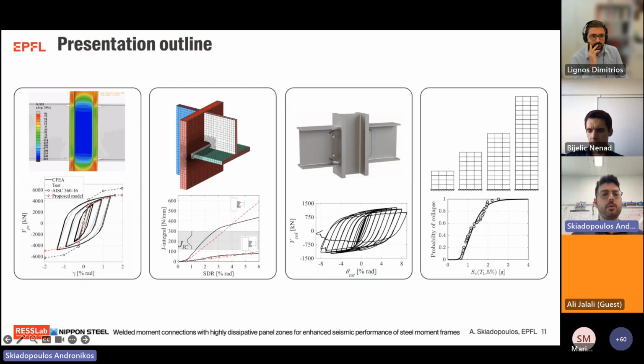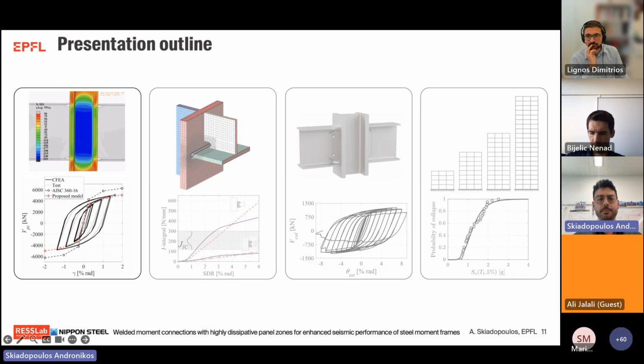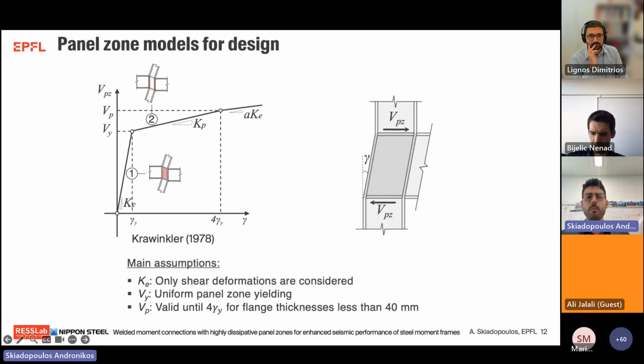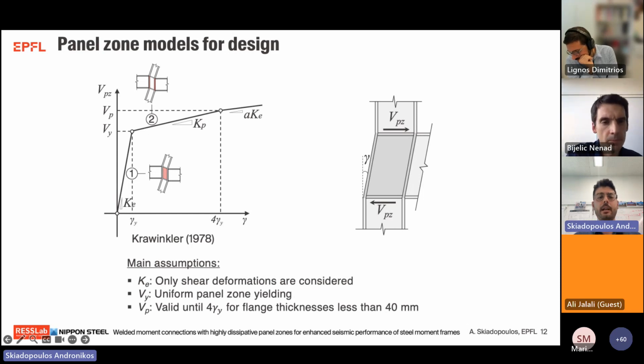Moving forward to the panel zone model development. Panel zone models historically comprise 3 branches, with the first one being the elastic one. So this one assumes uniform panel zone shear yielding at Vy, where the contribution of the column flanges is disregarded. With regards to the panel zone elastic stiffness Ke, this is computed based on the shear deformation within the panel zone, where in this case the bearing deformation mode is disregarded.